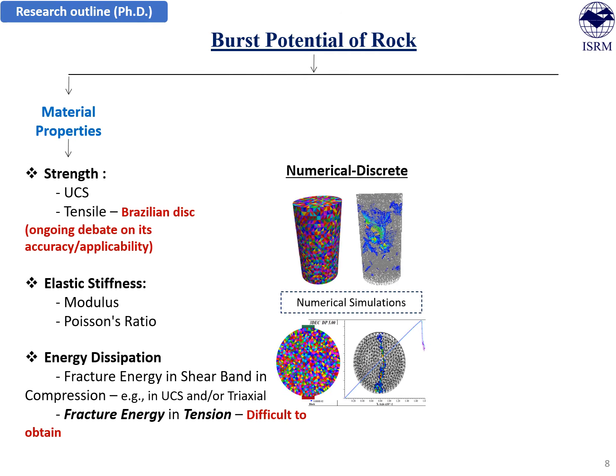In terms of tension, we have the indirect tensile strength test. That's called the Brazilian disc test. Now, the applicability or the reliability of its tensile strength estimation has been under debate for very long because it depends on the crack initiation point. In the literature, it's been established that if the crack initiates at the center of the disc, then the corresponding result for tensile strength estimation is reliable, else it is not. So that was one thing we need to focus on in this research.